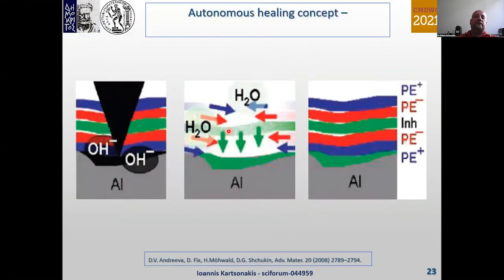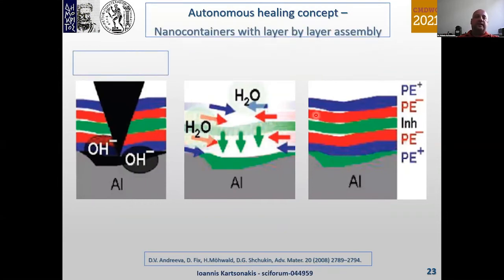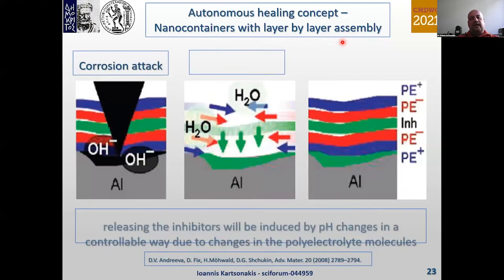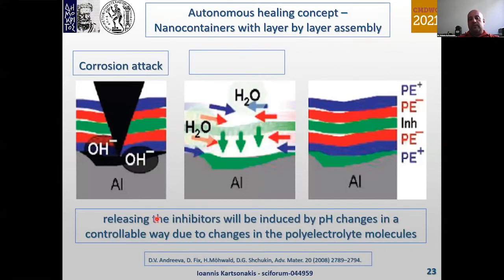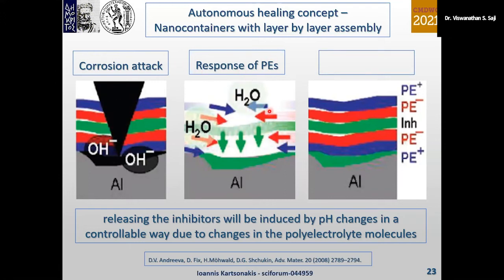Regarding autonomous self-healing coatings with nanocontainers with layer-by-layer assembly, the release of the inhibitors will be induced by pH changes in a controllable way due to changes in the polyelectrolyte molecules. There is a corrosion attack, response of polyelectrolytes, and then there is the self-healing.